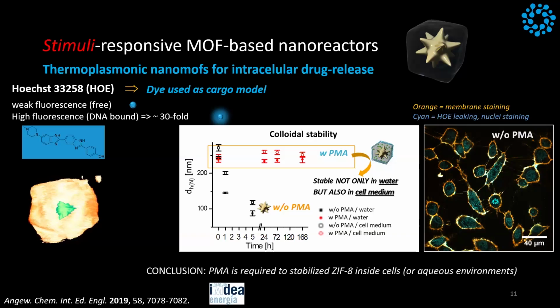In my opinion, by thermodiffusion, we're going to be able to expel, to release what we had encapsulated inside the MOF. Okay, MOF, in this case ZIF-8, has small pores of about 0.5 nanometer, 1 nanometer, and you can encapsulate a lot of different molecules. The kind of molecule that we wanted to encapsulate, in this particular case, is Hoechst 33258. If you are familiar with biology or whatever, this is what we use to stain the nuclei of cells. Basically, it has a very weak fluorescence, but when it coordinates with DNA, fluorescence goes up like crazy.